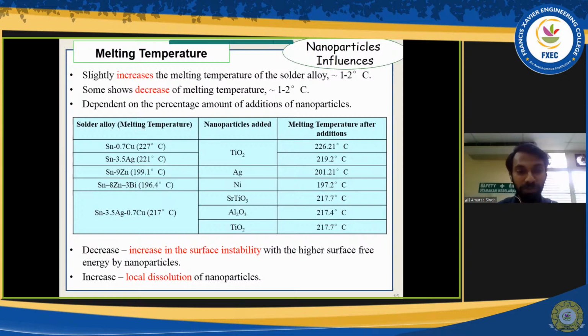So let's look at the decrease of the melting temperature first. Nanoparticles, when we add them, actually increase the surface instability of the solder alloy. That means the solder alloy will lose its energy earlier than without the nanoparticle additions. Therefore, the decrease happens. Whereas the increase in the melting temperature is because of the local dissolution of the nanoparticles in the solder alloy. For example, when we are melting the solder and adding the nanoparticles, it will tend to have, of course, a higher melting temperature. So they actually produce local dissolutions, so it slightly increases the melting temperature of the solder alloy. But not to worry, this gives us a good idea that addition of nanoparticles is not changing the melting temperature drastically. It's an important aspect to look into.